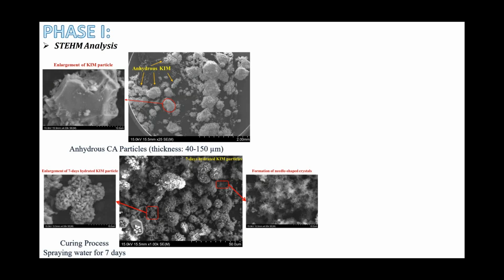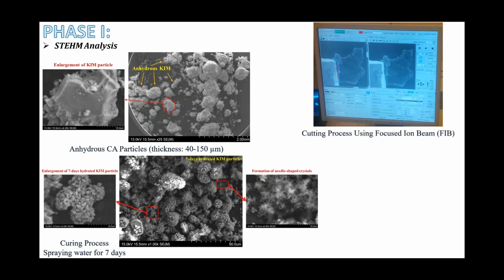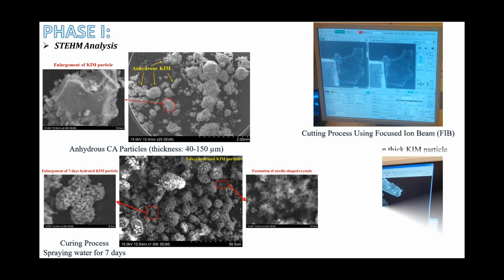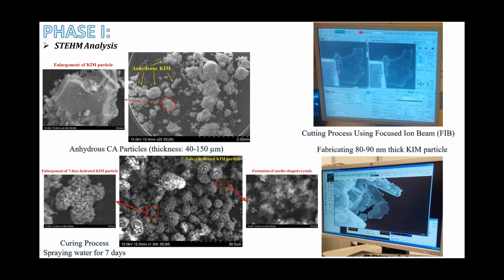But still, as I mentioned earlier, there is an issue when you want to see the internal structures of your particles. The sample size that can be fitted inside the TEM should be less than 100 nanometers. To satisfy that, I used the focused ion beam, which is a micro milling machine, and I cut the particle to have electron-transparent samples, as you can see in the photo. This is the view in our STEM, and you can simply say the particle has been cut to the degree that we can see inside.